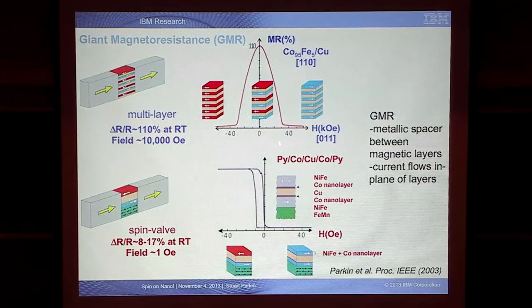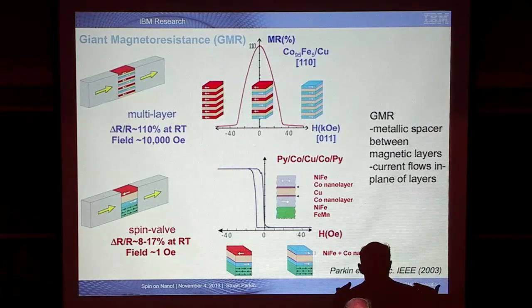And when you now apply a large magnetic field, about 40,000 times the Earth's magnetic field, these ultra-thin, atomically thin magnetic layers, separated by atomically thin copper, can be reoriented so their moments are parallel, and the resistance of this multilayer drops. This is the resistance change in percent. So at zero field, this structure, in which the alternating magnetic layers have their moments anti-parallel to one another, has a resistance 2 times higher than in a large magnetic field, which is required to overcome the magnetic interaction through these ultra-thin copper layers. Now, Peter Grunberg and Albert Fert found this phenomenon at very low temperatures, well, not super low temperatures, not in this system, but in magnetic layers of iron separated by layers of chromium. And then I showed essentially that this is a universal phenomenon, and we could create materials that showed large effects even at room temperature.